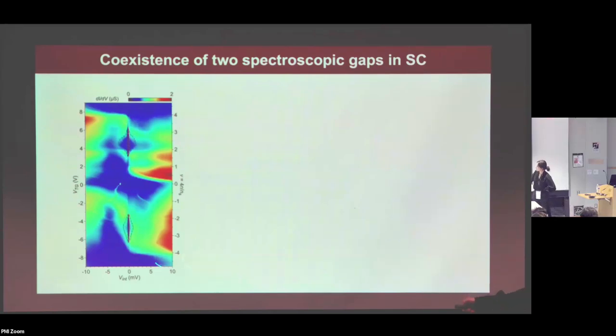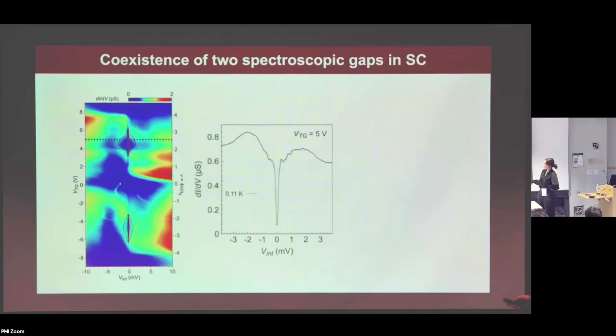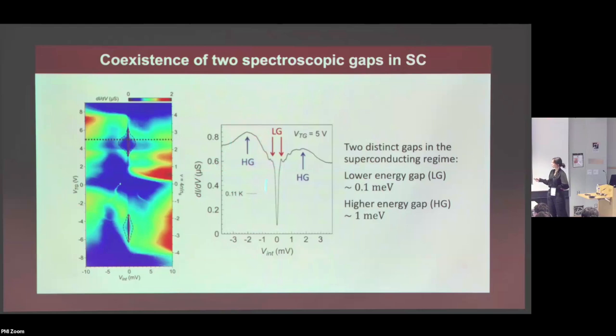But in addition to that, around a few milli-electron volts, there's also some sort of dip, some sort of depletion of the density of states around those dips as well. So we can take a line cut here, and we can actually see that there are two sets of features. One is this smaller shoulder happening around 0.1 milli-electron volt that we saw in the previous correspondence. But in addition to that, you also have these broader shoulders that are clearly two separate features from the low energy gap. Okay, so we see that in a single tunneling spectrum, we have two scales. One is the low energy gap scale happening around 0.1 milli-electron volt, and then separately there is this high energy gap scale that's like 1 or 2 milli-electron volts.